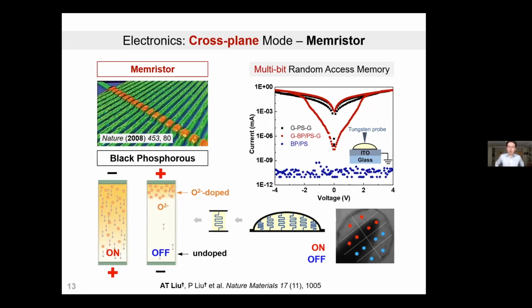Right. So it turns out, you don't want to go much more above this switching voltage. Because of the lateral high sheet resistance within the graphene, when it's fabricated in this form, the spreading current is such that you don't really affect the adjacent pathway by that much. But of course, if you want even better tunability of these digits, one simple way is to fabricate contact pads of different metallic contact pads, which our later work of electroplating smaller electrodes on top of the graphene can also be utilized for, in order to access even more stable digits and bits of memory.